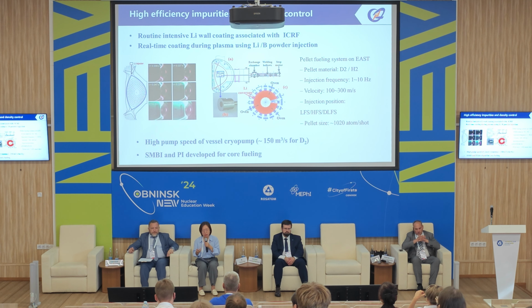For the long pulse operation, impurity and density control is also an important issue. So we have the lithium coating technology for plasma conditioning and cleaning, which is carried out before the plasma discharge. And during the plasma discharge, we also developed real-time coating with lithium and boron powder injection. The figure shows the green light during the plasma. This shows the lithium injection in real time during the plasma discharge. And for particle control, we have the high pump speed of the vessel cryopump to remove the particles. And we have also developed SMBI and pellet injection for plasma fueling.